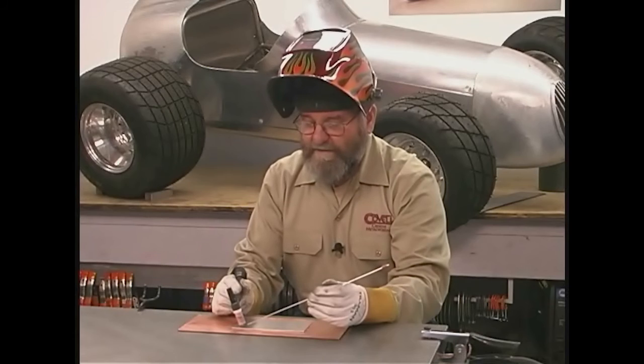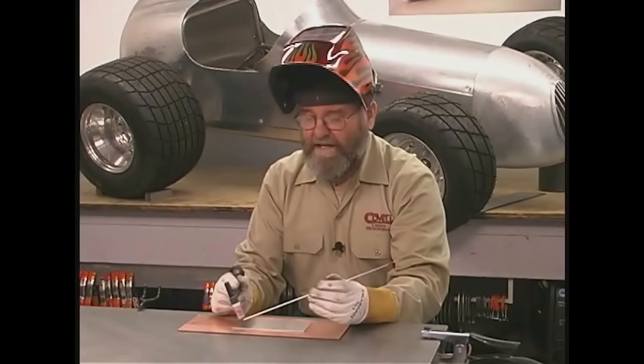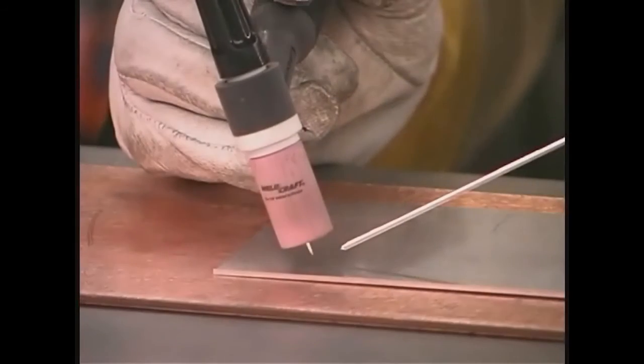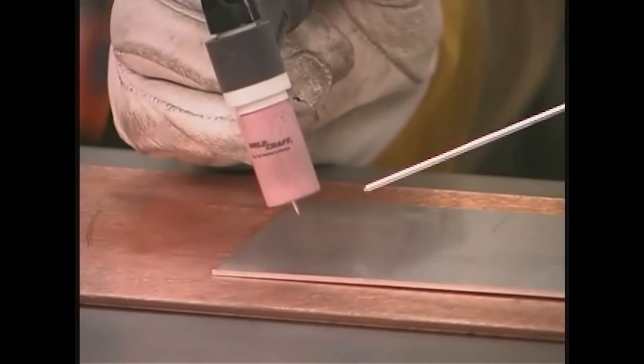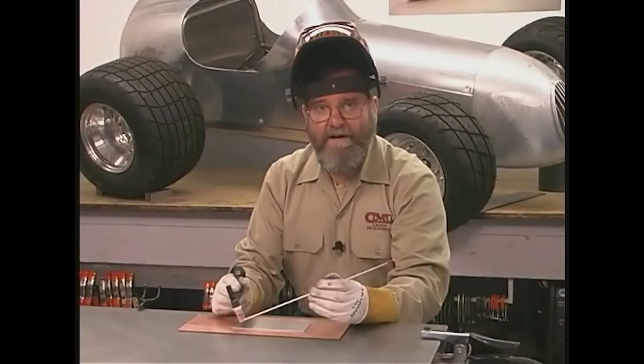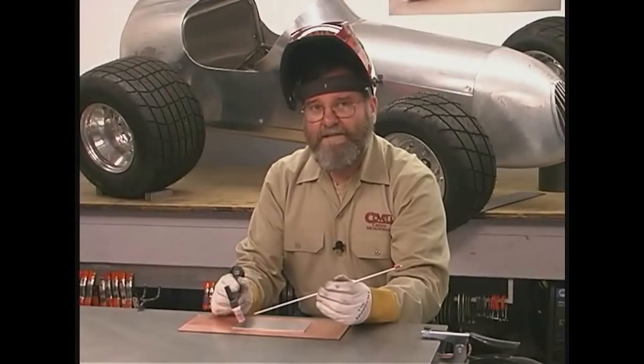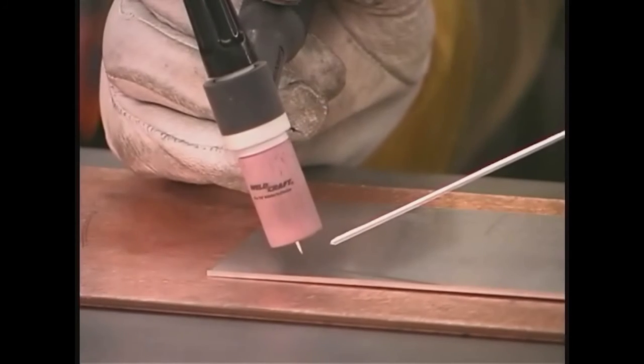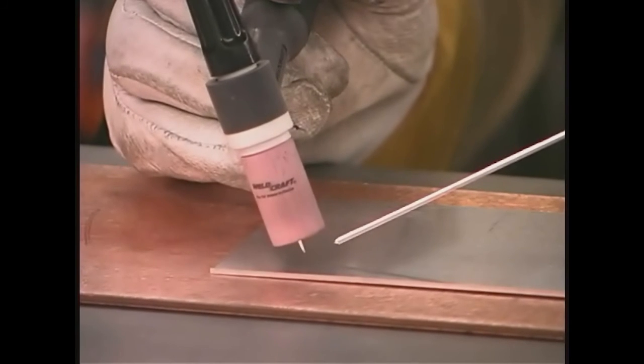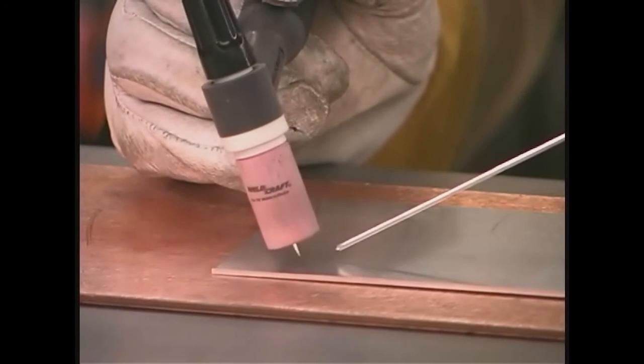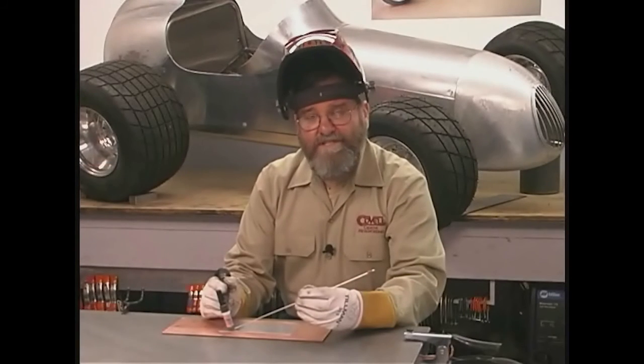The problem with having the tungsten too far away is that the arc shape is a cone, so the farther you pull the tungsten away, the larger the arc cone is where it contacts the metal. That makes your weld puddle unnecessarily large. So you really need to carefully control the distance between the tungsten electrode and the workpiece as you're running the puddle across the metal. I'm going to make a weld 2 inches long.